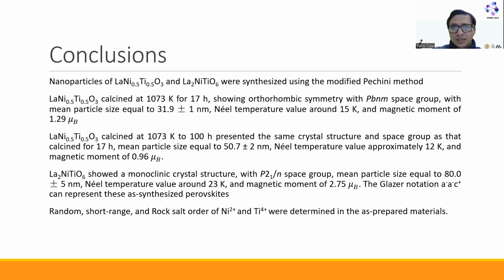The first one used a final calcination temperature of 800 centigrade for 17 hours, the second one employed 800 centigrade for 100 hours, and the last calcination condition was 1000 centigrade for 135 hours for obtaining sample 1, sample 2, and sample 3, respectively.